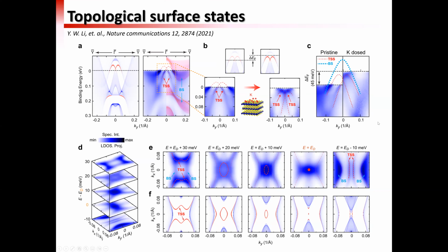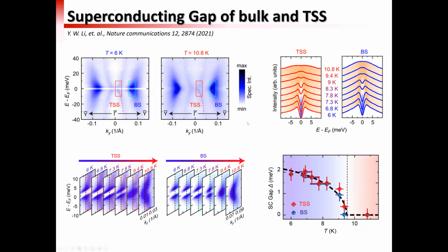So the next step is to see whether we can go into the superconducting state and check if the surface state also has the superconducting gap. For this sample, luckily the Tc is relatively high. We were able to get to 6 Kelvin sample temperature. And you can see in the temperature-dependent measurement that at 6 Kelvin, there's an overall gapped spectrum. This is the symmetrized ARPES spectral map. You can see that there's a gap around zero energy, which is the Fermi energy. On the other hand, if we merely increase the temperature by less than 5 Kelvin, this gap disappears.